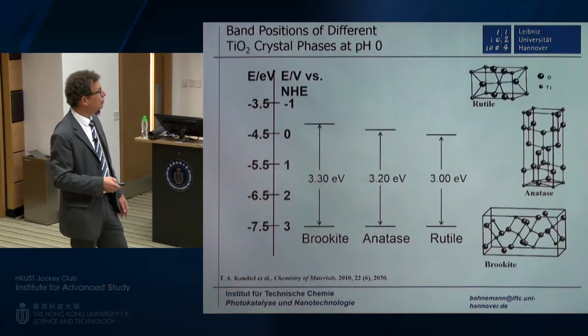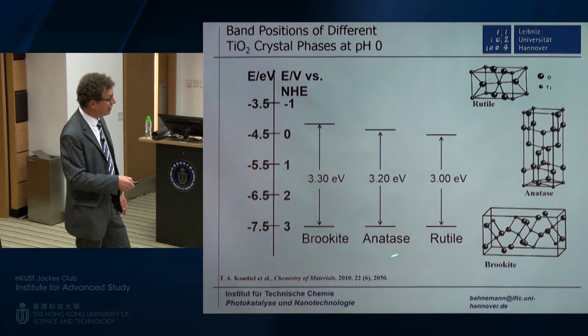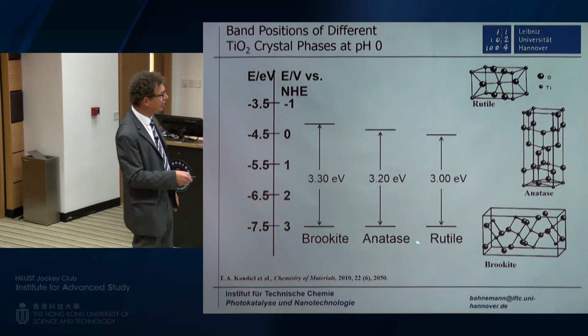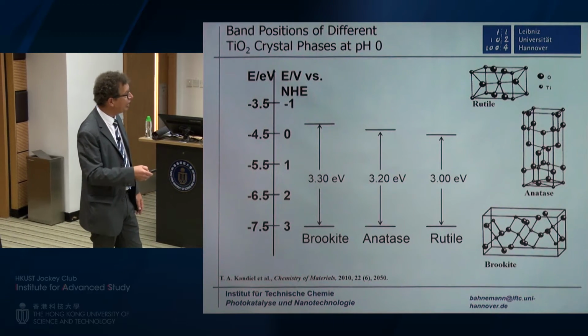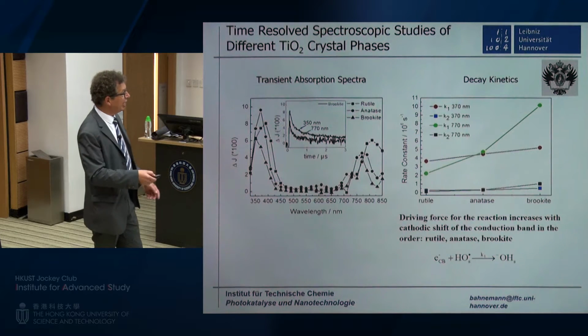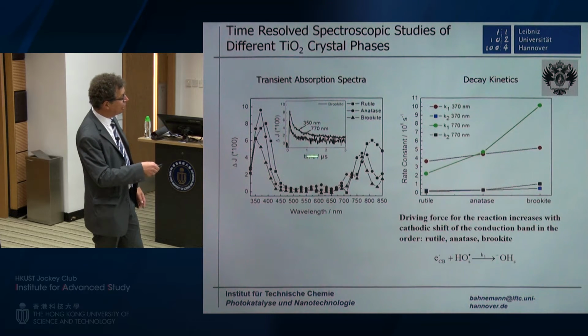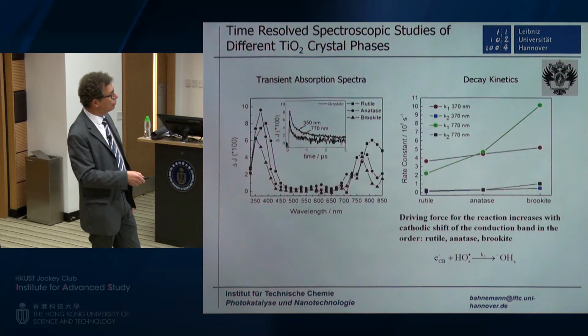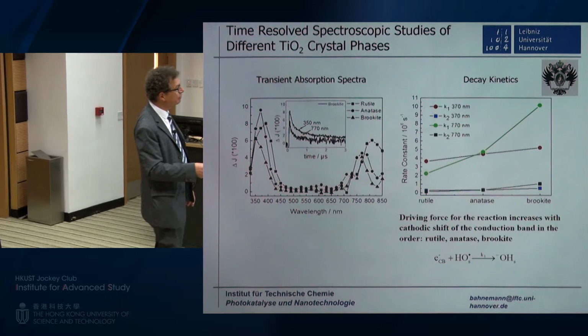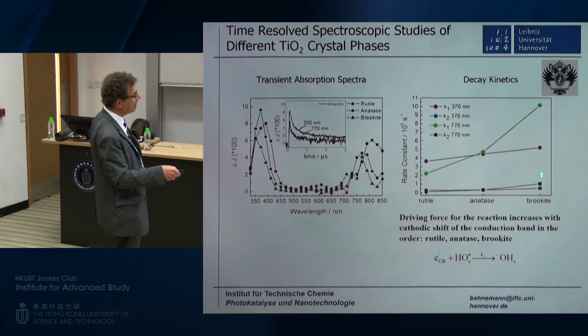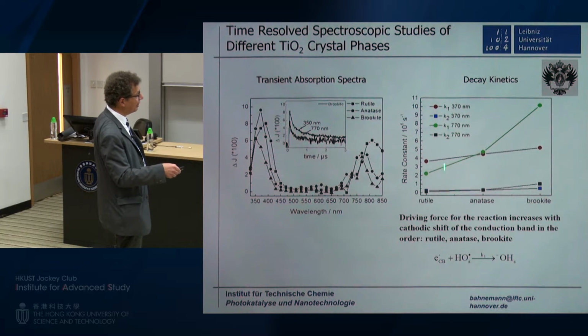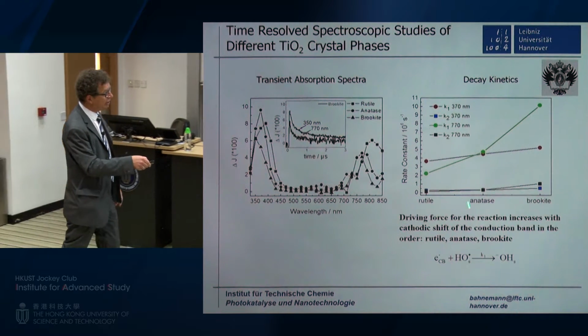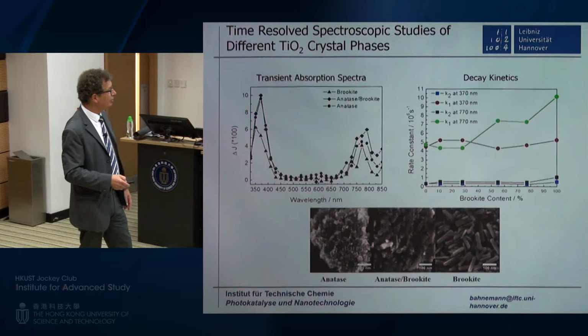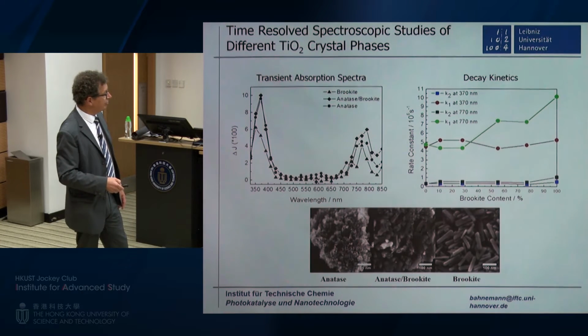Then we've also looked at other phases except for anatase. What I showed you before was pure anatase. We looked at rutile and brookite. And again, we did the studies. You see the maxima are shifted a little bit in brookite and rutile as compared to anatase. The kinetics in brookite are faster and in rutile are slower. Anatase is sort of in the middle. These are our particles that we looked at.